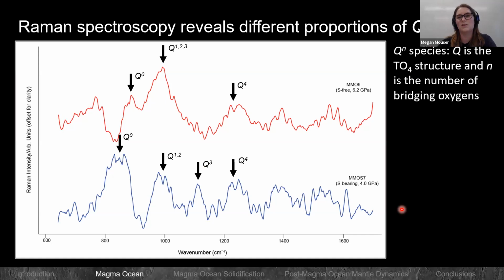And it really boils down to these Q species. Q species is the way to define the tetrahedral structures within these liquids. So Q0 is an isolated Q species, and as you increase, Q4 is a fully polymerized system. All of these Q species are present within this liquid to some degree. Some of their peaks shift a little bit, probably due to the pressure in the system.